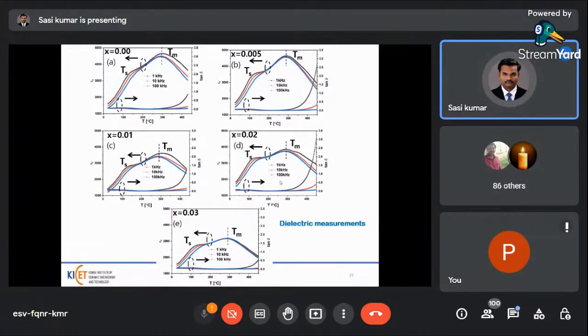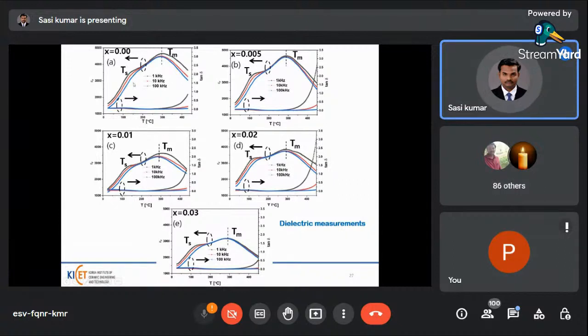And then these are the dielectric measurements of NBBT, yttrium, Sb doped materials for different compositions. Here the dielectric spectra give two different dielectric anomalies. First one, around 150 degrees, shows the TS, a shoulder peak, and another dielectric peak shows around 300 degrees. This is the Curie temperature of this material. The rhombohedral structure changes into the cubic structure, and TS is mainly due to the nanopolar regions of the rhombohedral structures in that material.